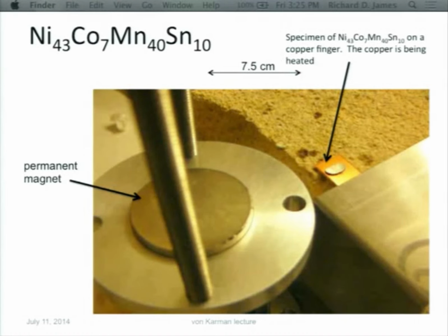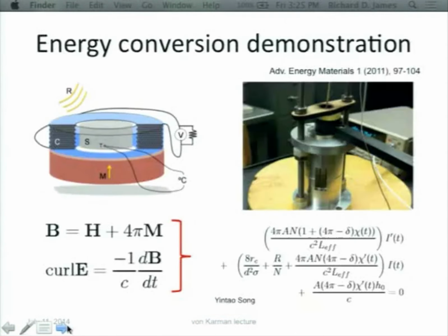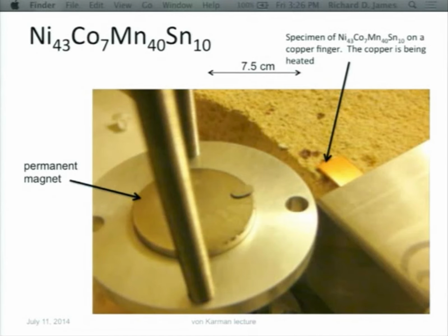That's a sample of that material, nickel, cobalt, manganese, tin, and it's sitting on a little copper finger, and that's a permanent magnet. I'm just going to heat the copper finger, just so you see how it goes here. Okay, so it's kind of silly, but you can see that even though it's pretty far away from that permanent magnet, that's not particularly strong, it's enough to magnetize it. And then it follows the field lines over to the magnet. So if you imagine turning that on 90 degrees, it would be an example of energy conversion, because heat would be effectively converted into kinetic energy, and then as it got to the top, potential energy.